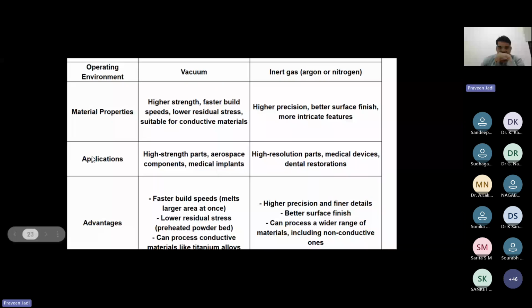Operating environment: if you go for EBM technology, the chamber atmosphere is vacuum. If you go for LPBF, it is an inert gas such as argon or nitrogen. Depending on the material, you can use the gases. The metal properties in EBM are higher strength, faster build speeds, lower residual stresses, and suitable for conductive materials. But LPBF has higher precision, good surface finish, and is used for more intricate parts.